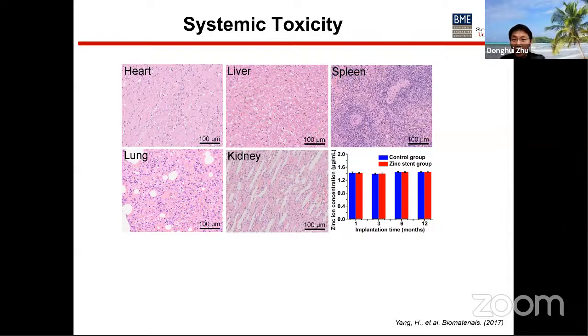Lastly, we checked the systemic toxicity of the implants. So far, we observed no infarction, histological changes, or corrosion product accumulation in the internal organs. All these organs look very normal, with healthy histological morphology. No significant difference in the blood level of zinc ion was observed compared to the control. So far, no bigger concerns about systemic toxicity due to the degradation product released from the zinc implant.